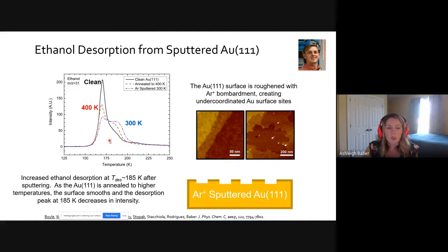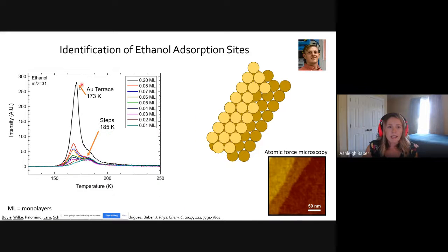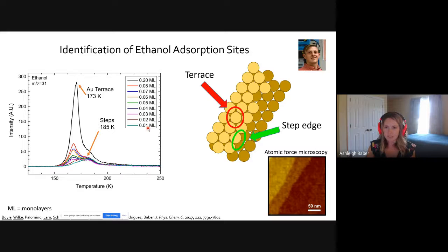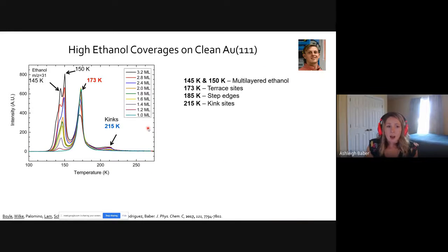If we're looking at low coverages of ethanol, we can generally see a little shoulder here in this peak. So we can assign the 173 Kelvin to gold terraces. If you're thinking about that on the atomic scale, moving away from a step edge where you have a higher coordination of gold atoms, you could have an ethanol sitting kind of far away from the step edge on the terrace site, as compared to ethanol sitting directly on a step site where you would have a lower coordination. Those molecules are going to be bound a little more tightly, and so we'll see molecules desorbing at higher temperatures versus step edge site.